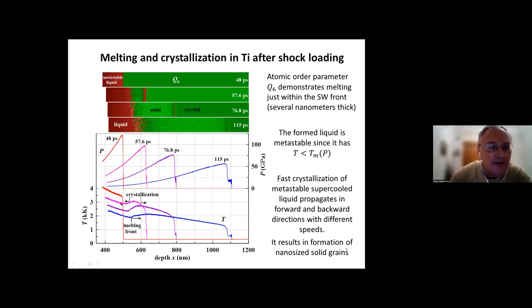If we pick up the temperature of this liquid and pressure, we may compare with the melting line. And we immediately found that the material here, the liquid state, is below the melting line. So it means it stays in the supercooled metastable state. With the decrease of the temperature here, the supercooling degree becomes very high, and nucleation and crystallization of the solid phase start. Crystallization fronts propagate in backward direction and forward direction, following the shock front. At a depth of about 800, the amplitude of the shock wave becomes too low, and this cold melting just stops.